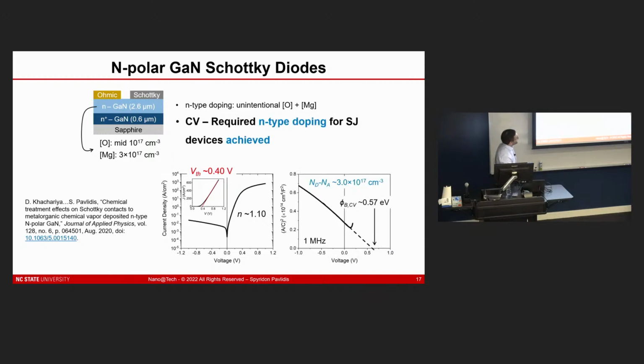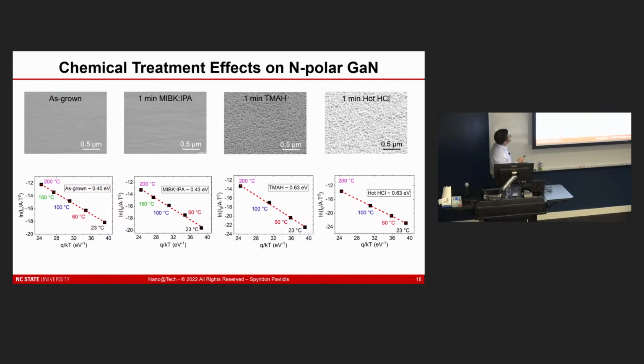We also, in this same paper, did CV, and from the CV we could confirm that with the growth conditions that were used, we now had N-type doping in effectively the 10 to the 17 range. So this was in that range that we needed to be able to make these superjunction devices down the line with high voltage behavior. Another important study that we did as part of this paper was looking at the impact of our processing. Conventionally, when you make a high-quality Schottky contact, you want to prepare the surface before metal deposition, and that often involves treating the surface with some sort of acid to clean up oxides or residual carbon, for example. And a very common way of doing that is a hot HCl bath.